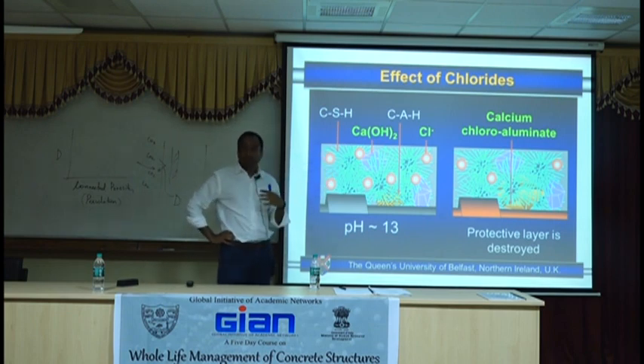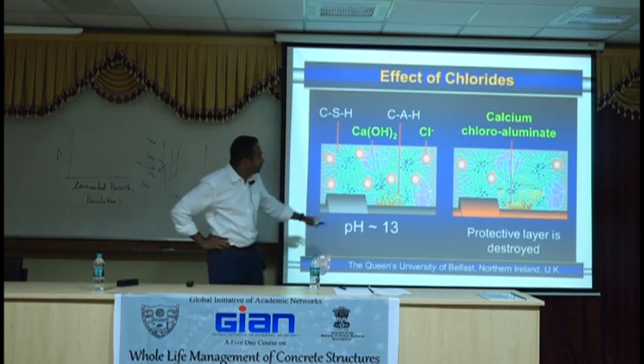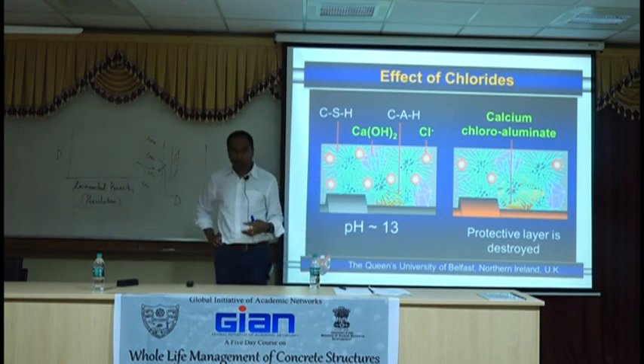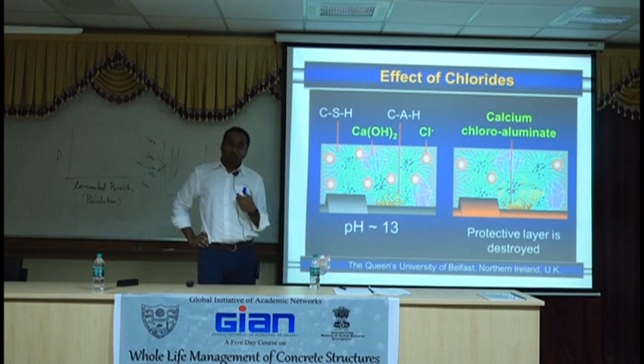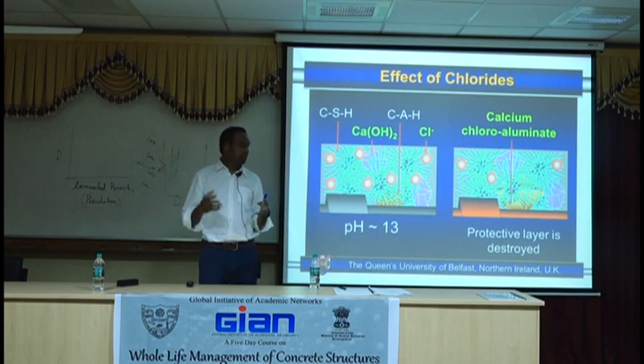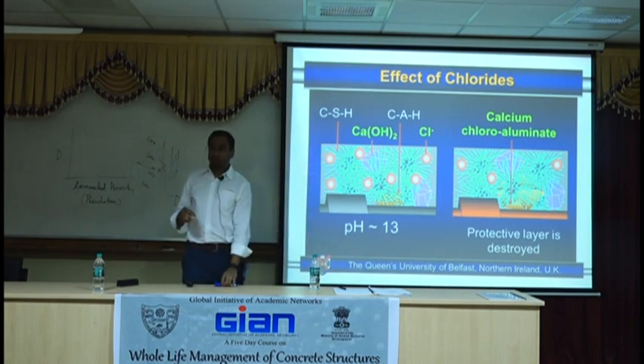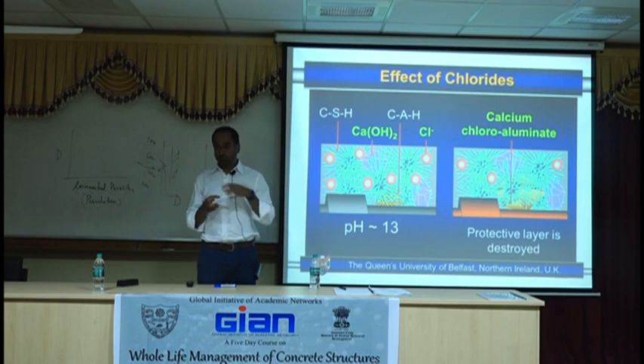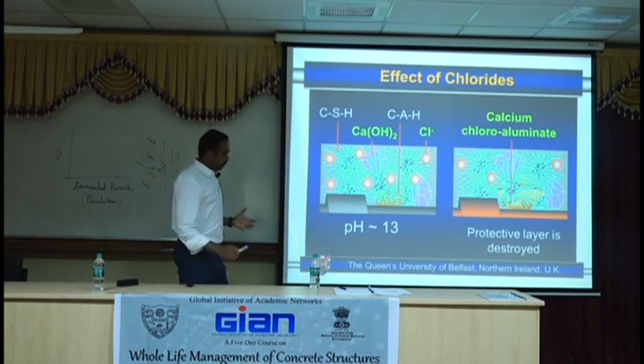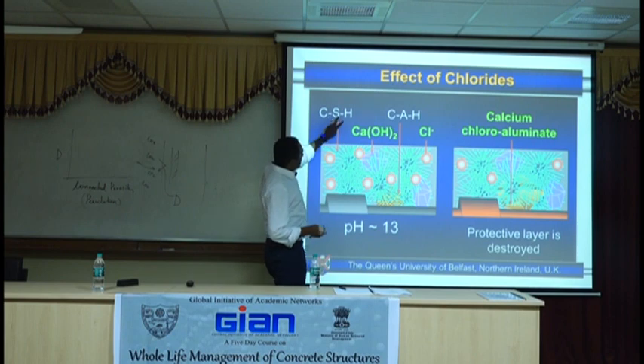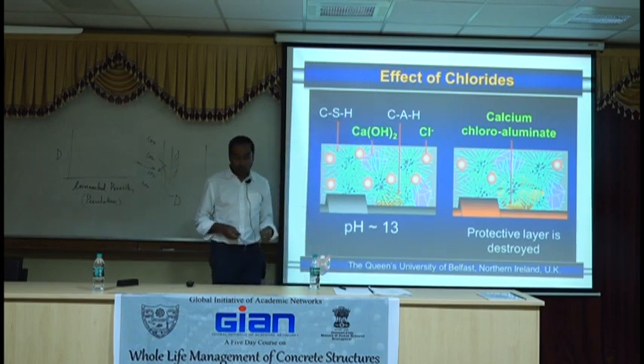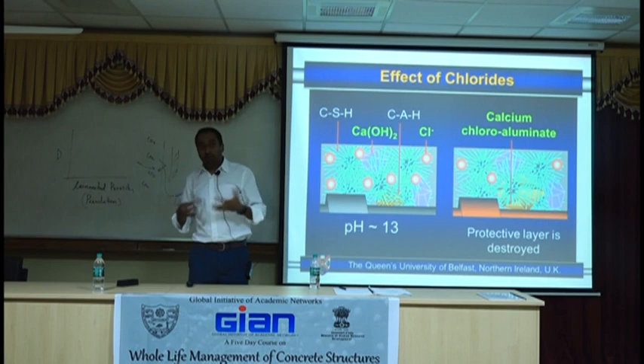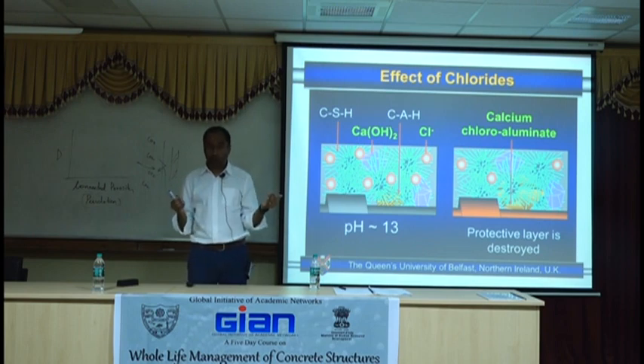and the chlorides will start to react with some of the phases. What we know is it will react with calcium aluminate hydrate and it forms Friedel salt. We're also now nearly agreeing that it will be combined with calcium silicate hydrate in a more physically absorbed form, not a chemically bound form. So the more calcium silicate hydrate and the more calcium aluminate you have, the better its capacity to hold chlorides. Aluminates are great in the sense it's chemically converting it, so it's a more stable compound.